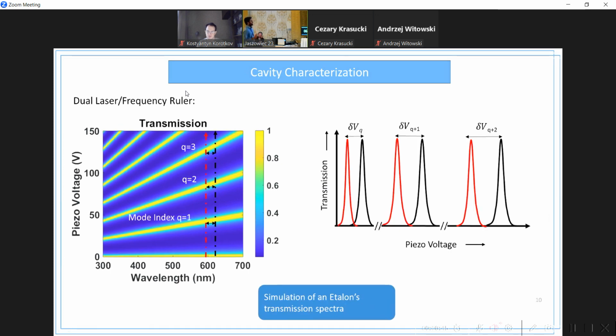We fix one laser, we scan the second dye laser across the HeNe laser, and we measure the corresponding differences in the peaks, in the center position of the peaks - this delta V corresponding to each mode.